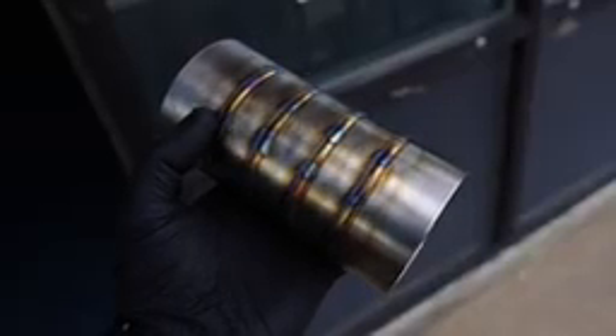Alright, so let's recap. Material prep and fit up are absolutely most important. Take the time to make nice parts, even for practice. Tack weld placement can 100% reflect how your end result looks. If you weld from tack to tack and you have multiple joints close together, line them up. Cup size varies on your stainless tube's diameter. Make sure you are back purging all of your parts.